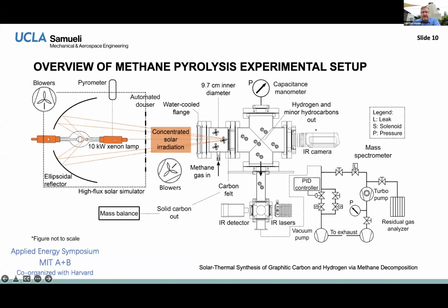But the nice thing is that by having a geometry in this way, we can actually look at the back of the target. So this is the absorber and the deposition surface, and we can look at that with an infrared camera. And then the flow proceeds out, and we do a lot of chemical diagnostics on the exhaust stream, and you'll see a lot of results from that as we go through this.